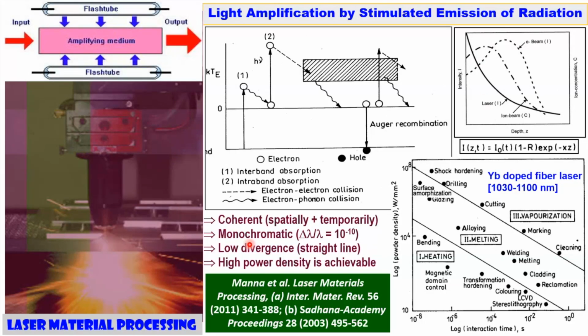So the entire energy is absorbed primarily in the near-surface region. With this coherent, monochromatic, low-divergent beam with very high power density, we can play with only two independent process parameters: the interaction time and the power density. By controlling and selecting these two in the right combination, you can process only in the solid state, involve melting followed by solidification, or go into the vapor state and then deposit to form a solid layer. So essentially, you can deal with solid without melting, melt and solidify, or deal with very high melting solids, take them to the vapor state and deposit as a layer or film.